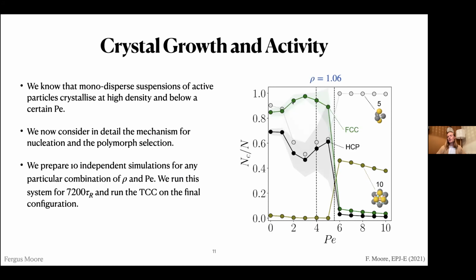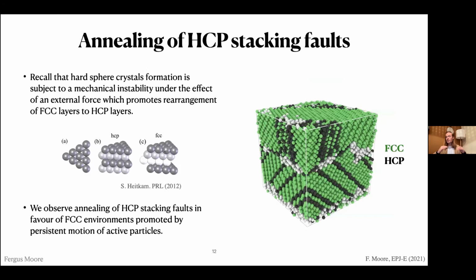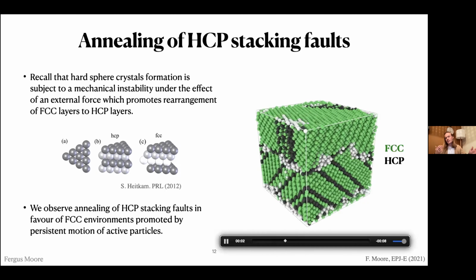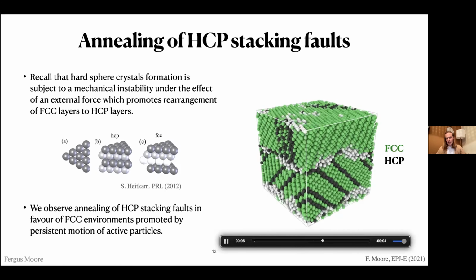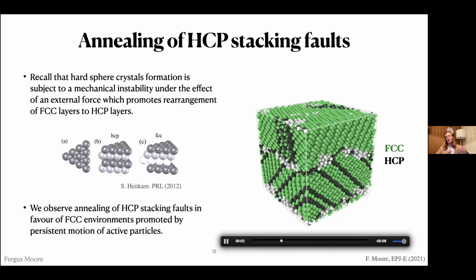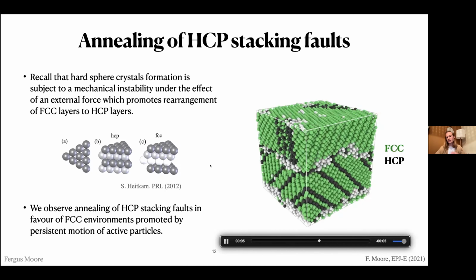So why is this FCC prominence happening? Well, it's to do with these layers that I was talking about before. So we can see that HCP looks like this and FCC is like this, and HCP has a slight mechanical instability that is slid across due to the promoted persistent motion of active particles. So I have a little video here. The green particles are FCC and the black particles are HCP and white are non-crystalline. And I want you to look in this region here where particles are going to be active and moving, and you'll see this annealing of the HCP layers into FCC. So you see it happening here. And over a long time, this will continue, and HCP will be slowly weeded out of this crystal as it coarsens.